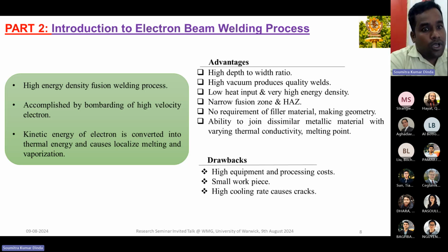But we have, say, DAE lab, Department of Atomic Energy of Government of India. They have one electron beam welding machine where the vacuum chamber is so big that four to five people can go inside, fix the material, and come outside. Then make the vacuum and then they do the welding. So they try to solve this size issue. And definitely there is a high cooling rate for electron beam welding, which is a problem because high cooling rate may sometimes create different types of crack.